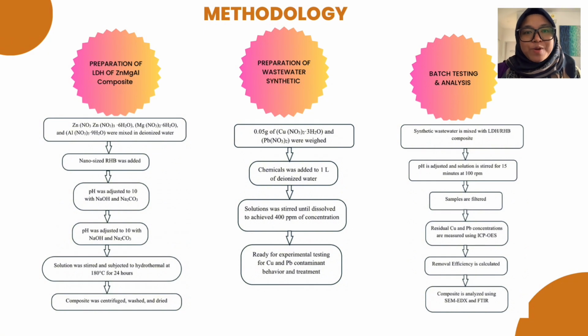The composite was prepared by mixing zinc, magnesium, and aluminium nitrates with rice husk biochar, and the mixture was subjected to hydrothermal treatment at 180 degrees Celsius for 24 hours. And next, we move to the preparation of synthetic wastewater. The synthetic wastewater containing 400 ppm of copper and lead ions was prepared for the test of the composite